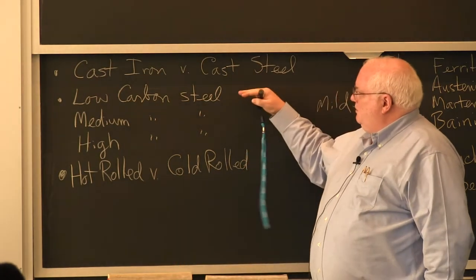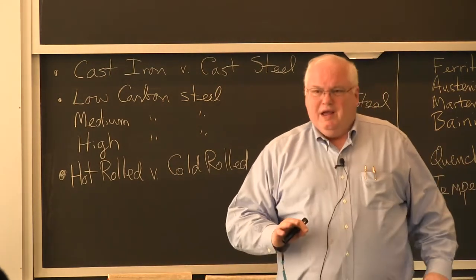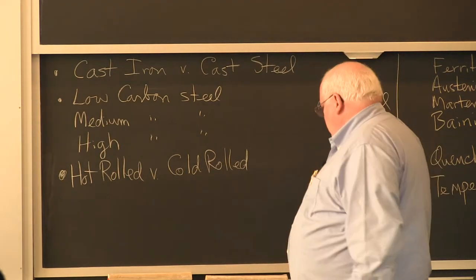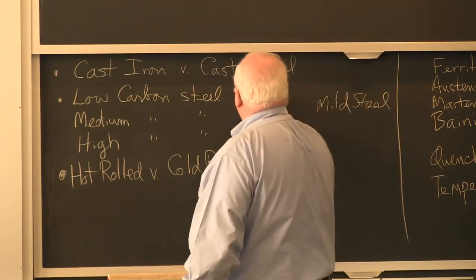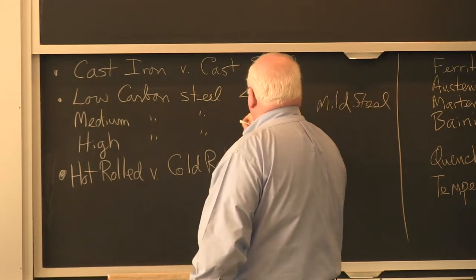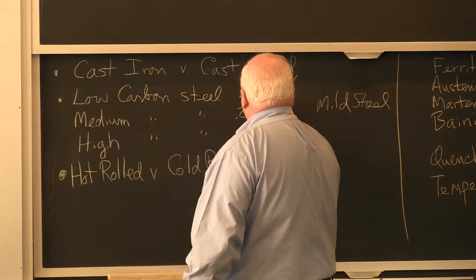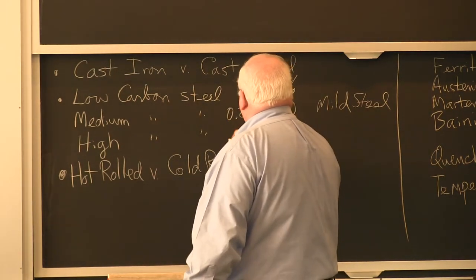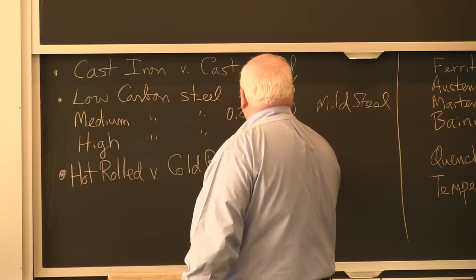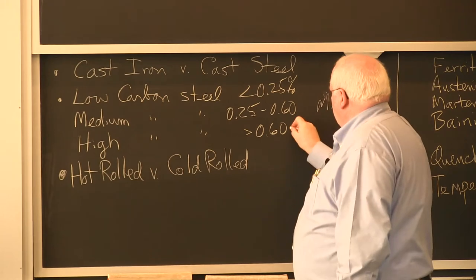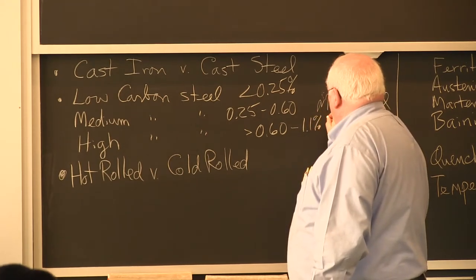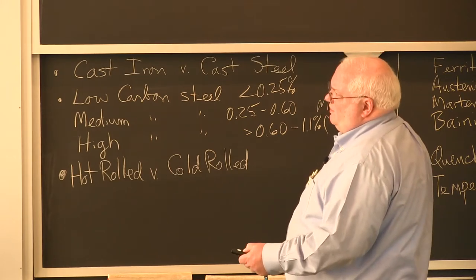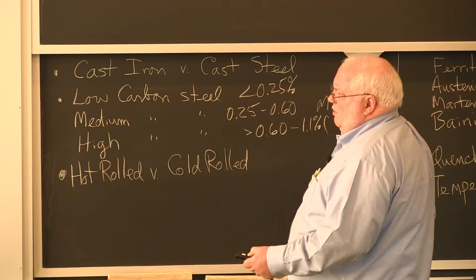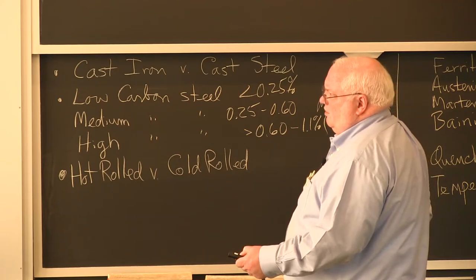And there are three types of steel: low carbon, medium carbon, and high carbon, that we call them today. There's no firm dividing line, but typically low carbon is something less than about 0.25%, less than a quarter percent. Medium carbon is about 0.25 to 0.6, and high carbon is greater than 0.6, and you never go above about 1 or 1.1% carbon in steel. You actually can go higher if you look in this region, but you don't usually go much above 1%, which is right in here, so, okay? You can get 2% in here, but there's only some tool steels and other things that have that much carbon.